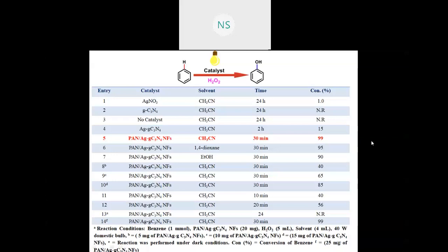So here benzene, the same condition is there, and we obtain... If you look into this particular fifth entry, same solvent, 30-minute reaction is there. If you look into the previous four reactions, 24 hours, 24 hours, 24 hours, 2 hours. When we used the same nanofiber by changing the solvents, only 30 minutes is required, but the conversion rate is 99%. Conversion of the benzene is 99%.